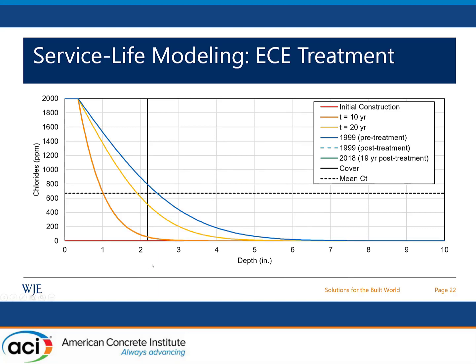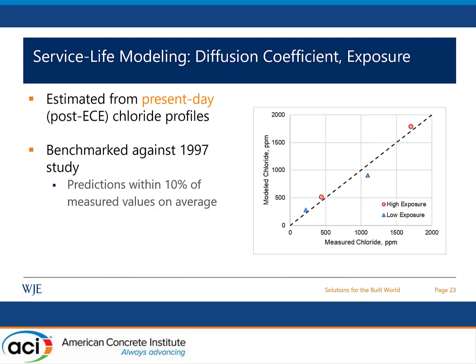Once the ECE treatment is applied, we consider there to be a reduction in the chloride concentration. We assumed an average of about 60 to 70% reduction based on the measurements that were performed by the party that had performed the ECE treatment in 1999. And then this modified chloride profile is progressed forward in time so that we could obtain estimates of what the current chloride profiles are and compare those to our models.